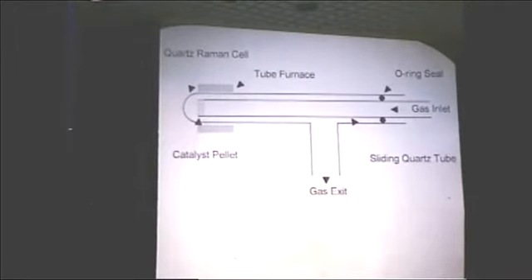And now we have the furnace up where the catalyst pellet is. And so we can heat the catalyst and we can run the catalytic reaction under reaction conditions. He's looked at the sulfated zirconia catalyst when the catalysts were at 500 degrees C in the pre-treatment oxidation. He's looked at them at 180 degrees C when we were coking them up with our contaminated butane. You could see the coke band grow in as a function of time. He could follow the transformation of the coke as a function of time online under reaction conditions.